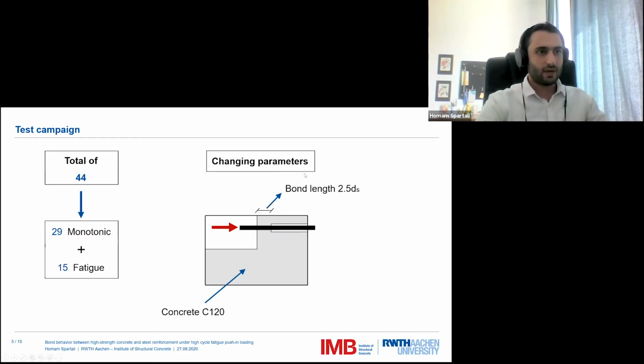Let's see what parameters we have changed. In the case of concrete C120, we changed the bar diameter. So we used the 16 and 25 millimeter bar diameters, but we kept the bond length constant, 2.5 ds.